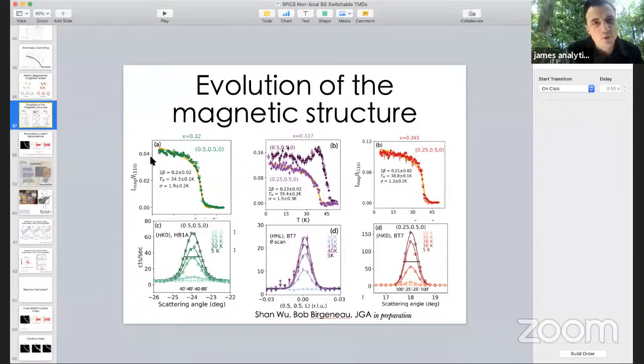Even though you have multiple order parameters that coexist and presumably have their own domains, we don't have any relaxation dynamics or any long time dynamics that we do see in the samples that have been deliberately disordered, which have just one order parameter. We don't have any history dependence of the magnetization or anything like that. So as far as we can tell, there's no glassy-like dynamics for this environment. We just have two coexisting order parameters, and everything else is very sharp.